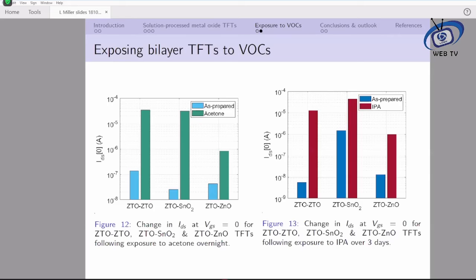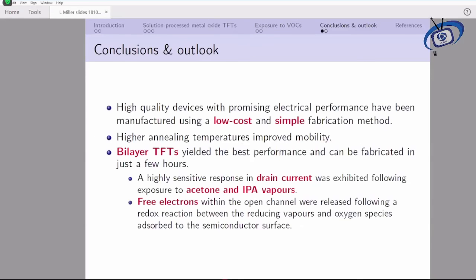To conclude, I have successfully fabricated metal oxide thin film transistors and extracted key parameters. I have achieved the highest mobility to my knowledge for ZTO thin film transistors. I have also found that annealing films at higher temperatures and spin coating an additional active layer resulted in improved mobility and near 0 volts turn on.